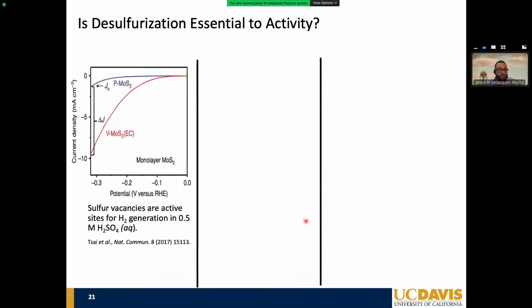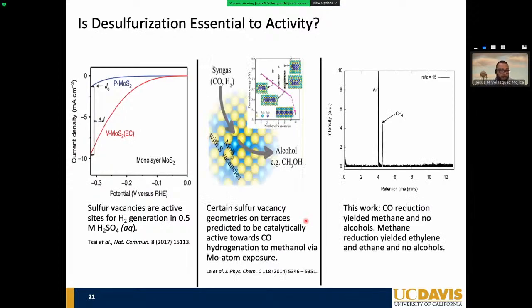So do we need the desulfurization to happen? Well, there's a couple of examples out there that talk about this, specifically on the hydrogen evolution reaction. There is some evidence that if you increase the population of sulfur vacancies, you actually also improve the overpotential required for you to be able to split water and produce hydrogen, or to reduce H+ to H2, I should say. There's also some theoretical evidence on the arrangement of the vacancies. So if you could nucleate controllably on a surface rows of vacancies or zigzag interconnections of vacancies or patches, you could perhaps have a surface that allows you to do CO hydrogenation to produce